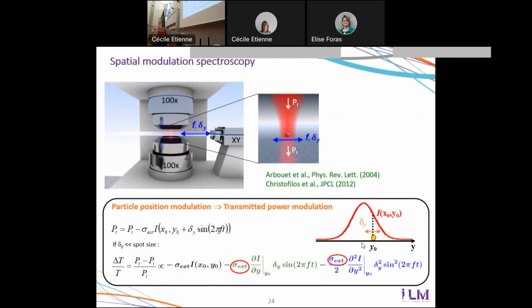In our setup, we have one objective to strongly focus light, and one objective to recollect the transmitted light. In between, we have the sample, which is typically made of nanoparticles deposited on a solid surface. And this sample is mounted on a vibrating stage, so it's moving like this periodically as a function of time. And when we do so, when there is a nano-object in the focused beam, the position of the nano-object is not constant anymore. So when it is close to the center of the beam, it will more strongly absorb and scatter light. When it is close to the border, it will less strongly absorb and scatter light. And as a result, the transmission signal that we measure is not constant anymore. It contains components at once and twice the modulation frequency that can be efficiently detected.